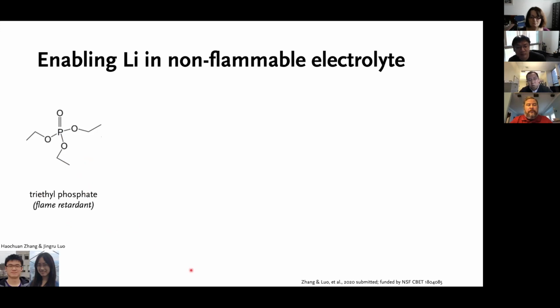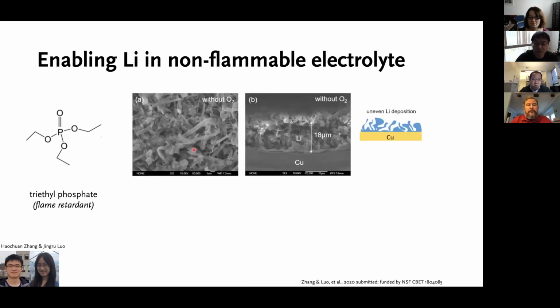But literature research has shown, and also Hao Chuan's research has shown, that when you try to directly use TEP with lithium, this is what happens. The deposited lithium looks like spikes. You get these beautiful rods. They're very loose. They really extend into the solution. This is bad for a number of reasons. In addition, this could penetrate through the separator and short the circuit, which is bad.